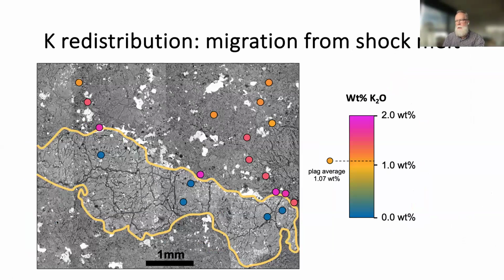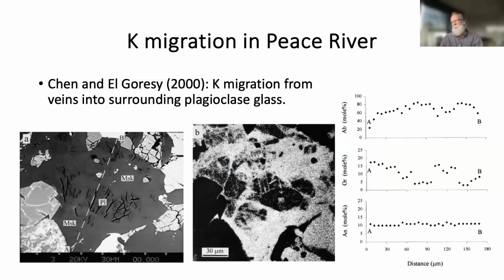So here's just another example of some values. You see the highest values of potassium are adjacent to the melt vein, the lowest are in the melt vein, and it tapers off as you go away from the melt vein. So it represents a migration of potassium away from the melt vein. But the question is when and how. Remember, this thing was probably at high pressure for on the order of a second. In that second, we quenched the melt vein and we drove the potassium out. And it's really odd. We migrated potassium on the scale of hundreds of microns in seconds. And we don't fully understand how this works, but we're working on it.